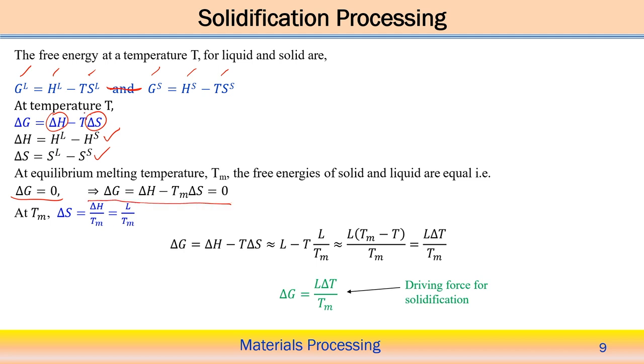So, basically solidification occurs at T equal to Tm, where delta G equals 0. We see that delta H minus Tm into delta S equals 0. From here we can see that at the melting point temperature Tm, delta S equals delta H by Tm. The change of the enthalpy is equivalent to the latent heat here, so delta S is latent heat by Tm.